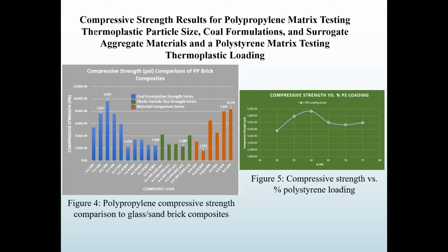And then in the orange, we have the material comparison series. In this, we wanted to test the wettability of the coal surface and the thermoplastic. So we compared it to analogous materials as the aggregate, such as glass and sand, and we found that the coal won out. So on the right, we have the compressive strength series of polystyrene loading. We needed to figure out the nominal loading of thermoplastic, before which we were testing basically the plastic buildup between coal particles, the shear force rather than the interaction between the coal and the thermoplastic.